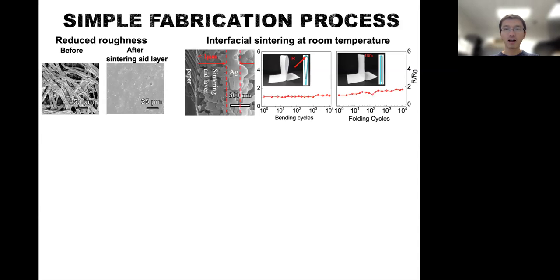thought of as a solid state diffusion. And the silver nanoparticle will be interacting with this nanocomposite through a very thin layer of the geometry. And that layer is about 1 micrometer or so. So even though we disperse nanoparticle up to tens of microns, only that 1 micrometer will be interacting with the sintering aid layer and be able to get sintered. And this thin geometry is really helpful because it becomes much more flexible.